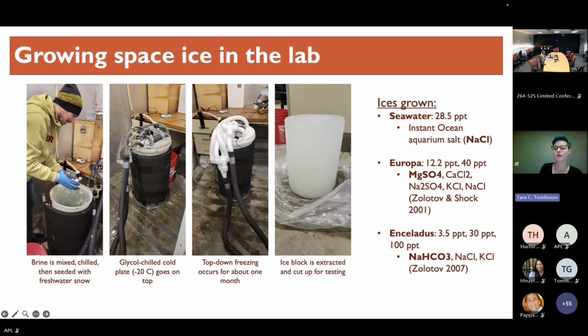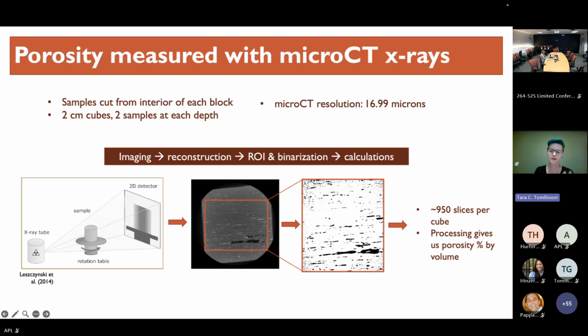So the way that we're testing for porosity is using micro CT, which is basically like taking X-rays of our ice to look at the interior structure. So to do this, we cut out 2 centimeter cubes throughout the depth of the block and then do it again. So we have 2 samples for each 2 centimeters of ice depth. So then each cube is scanned in the micro CT, which produces 2D images that can be combined and reconstructed to make the entire cube. So I will skip some of the details on that, but we do this for each of our ice blocks. That allows us to measure the porosity, and then we can compare them. So let's talk about what we found.